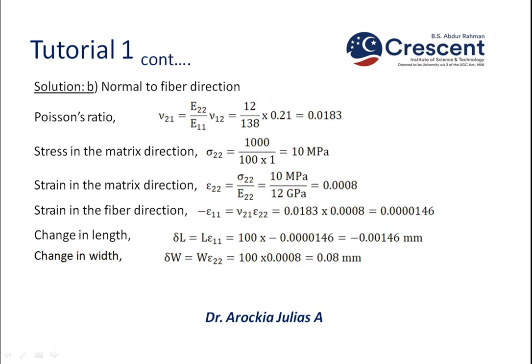So we have the relationship nu21 equal to E22 by E11 into nu12. Using that, we are finding nu21 as 0.0183. Now, similar to the previous case A, here we have to find stress in the matrix direction. So sigma 22 equal to load is same. So 1000 divided by, here the length and the width of the plate are same. Both are 100. That's why 1000 divided by 100 into 1, which again gives you 10 megapascal.